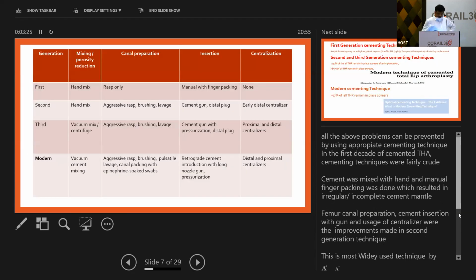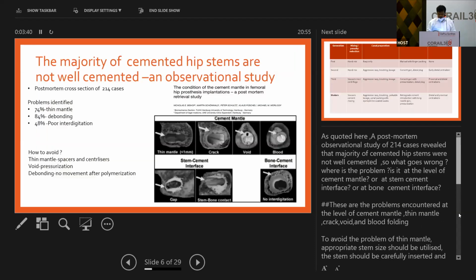At the level of the stem cement interface, the problem encountered is due to debonding. How to avoid debonding? At the time the stem is inserted into the cement, do not rotate it or use transverse movement, to avoid damaging the stem cement interface. How to avoid problems at the bone cement interface? Poor preparation and poor cement interdigitation cause them, so avoid these.